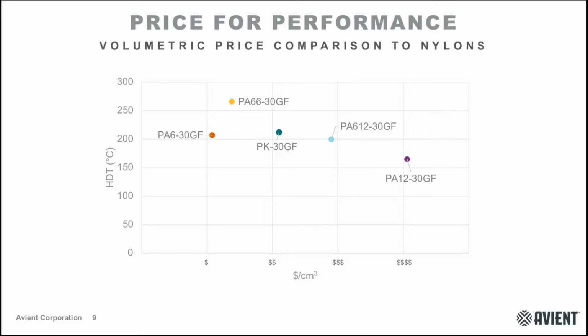Another factor to consider when comparing against this broad family of nylons is going to be the cost in use. So I already mentioned that polyketone resin is a little bit more dense than traditional nylons. It comes in at 1.24 grams per cubic centimeter, whereas your nylon 6 and 6,6 are probably closer to 1.1, 1.15, and your long chain specialty nylons are probably closer to 1. However, polyketone has a similar or better heat performance than those long chain specialty nylons at a lower cost. So you can wind up having a material that will satisfy your performance requirements at that lower cost. And again, these are all just relative price indicators. These dots might have shifted around since we made this graph up a few months ago. So it's something to consider when you're looking at developing with polyketone.